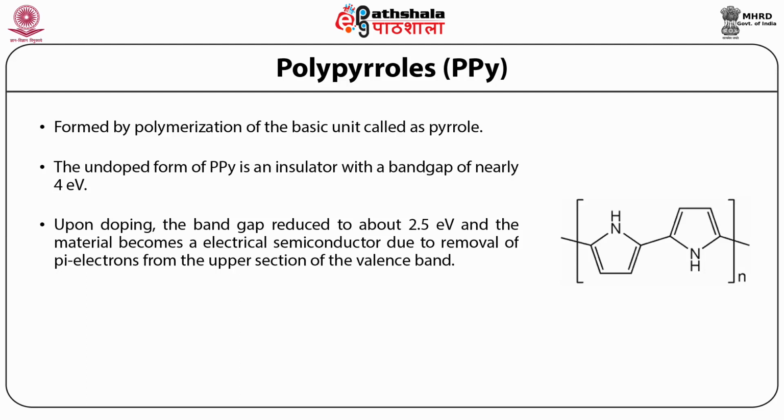Thin films of undoped polypyrrole have a yellow color which becomes darker upon the exposure to oxidizing, such as doping conditions, leading to blue or black films depending on the degree of polymerization as well as film thickness. Doping also tends to render the polypyrrole brittle. Also, both undoped as well as doped films have no solubility in the common solvents.